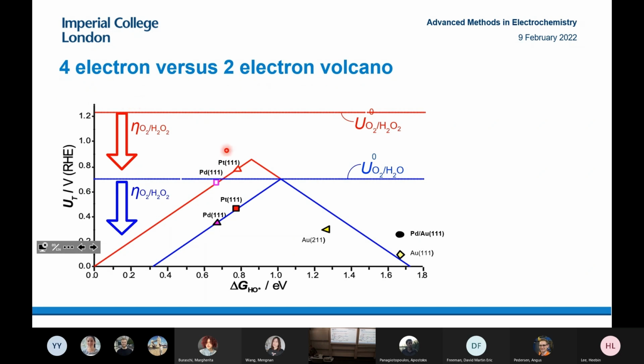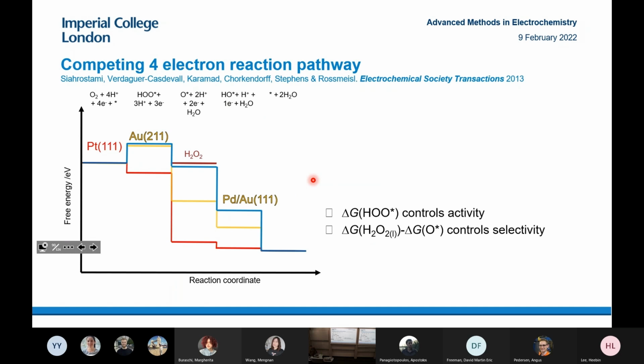So, in fact, this is a summary showing how the 4-electron volcano, in red, intersects with the blue 2-electron volcano for hydrogen peroxide production. Now, the potential for hydrogen peroxide production is 0.7 volts. So I already mentioned palladium gold nanoparticles for a slightly higher selectivity.